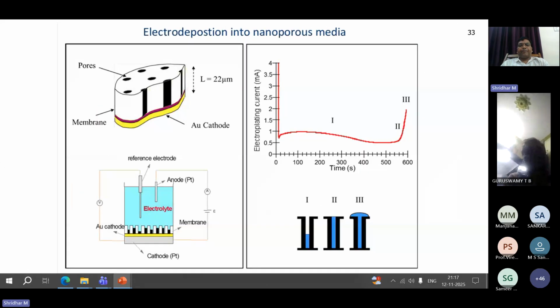Here you can see electrodeposition into nanoporous media. People are creating these nanopores to have a high specific area. That specific area will enhance the energy density or capacity, or give a high sensing rate when you create any sensor out of these materials.